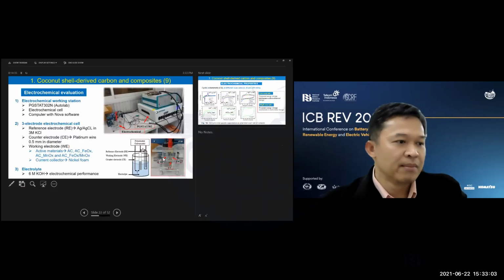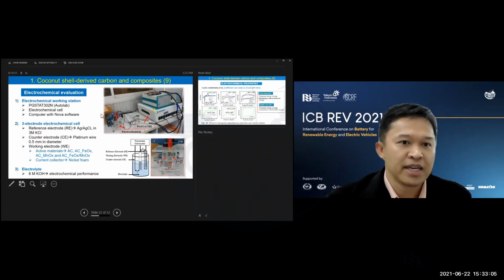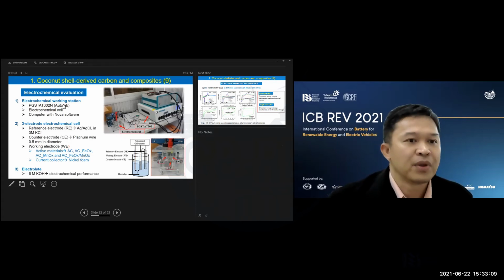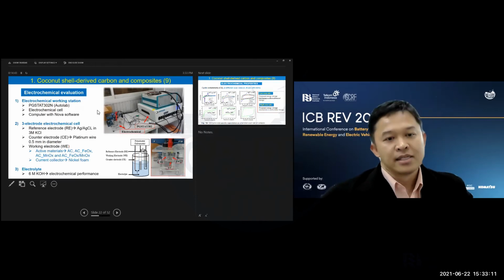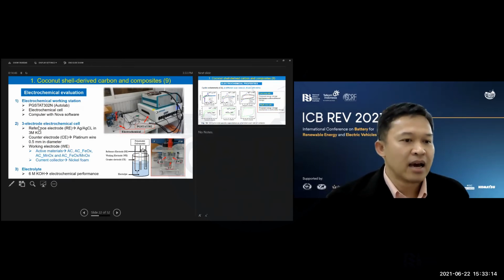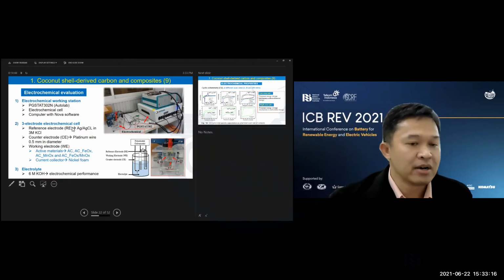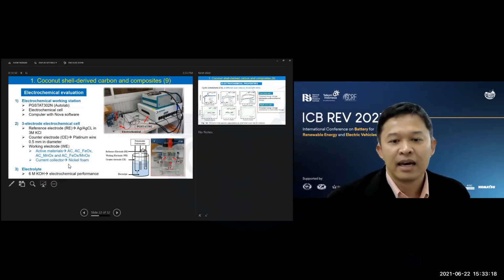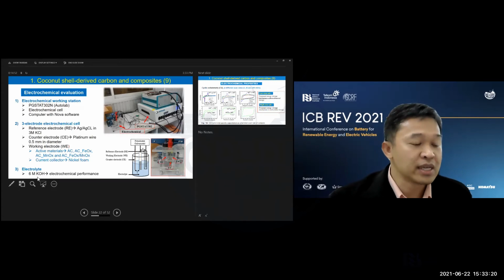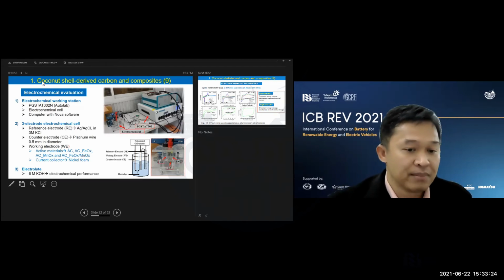So next, we measure the electrochemical properties of the samples by using the electrochemical workstation. We also apply the three-electrode cell technique. And for the electrolyte, we use 6 molar potassium hydroxide.